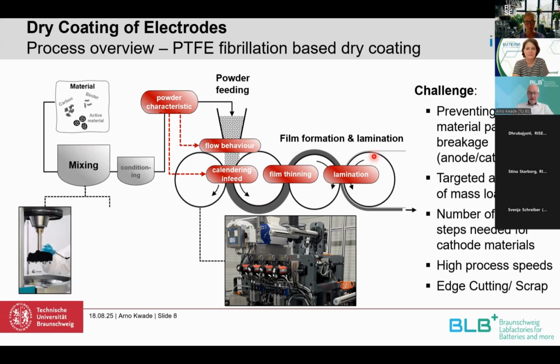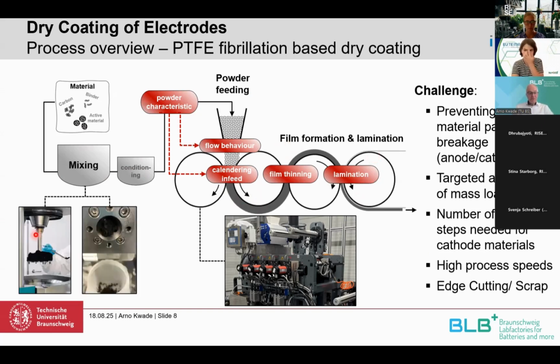In the case of mixing, we can also distinguish between batch mixing, like it is also typical still for wet processing, and continuous mixing, for example, by using extrusion machines. And what we have to do, we have to prevent the breakage of particles, for example, in the mixing step or also during the film formation.